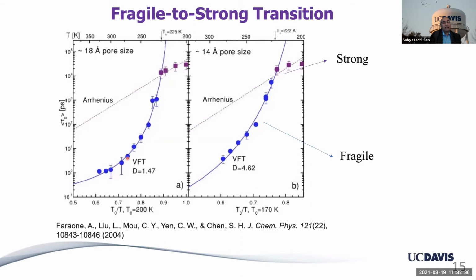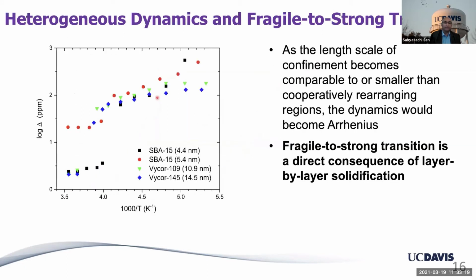The water signal, as water gets more and more strongly confined, beyond some point, since this is a layer by layer process, it is really confined not in the entire pore, but surrounded by the ice around it. And so it is very, very strongly confined, and therefore its entropy decreases because the available configurations decrease, because the confinement size becomes comparable to the cooperative rearrangement size, and then it becomes Arrhenius. So the layer by layer freezing provides a natural explanation of this fragile to strong transition.